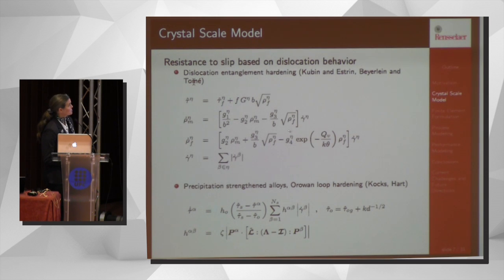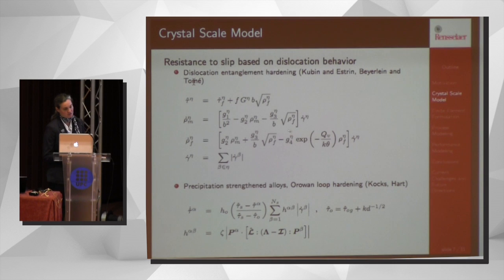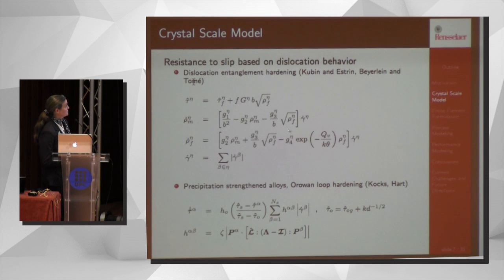Okay, so we group our dislocations by the type of slip system, so that's what the eta represents. For example, in a hexagonal material, we group the basal slip systems together, so when eta is 1, that might be the basal slip systems, and if we're looking at prismatic slip systems, eta could be 2, for example. We've also done some work looking at precipitation strengthened alloys. This involves the dislocations forming loops about particles, or precipitates to be specific, and of course those are there to give the material more strength.